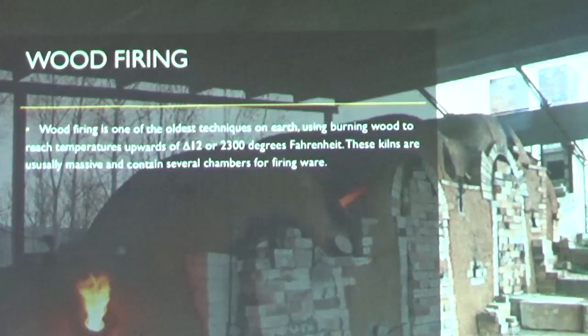This is one, as I said on here, it can reach upwards of cone 12, roughly 2300 degrees Fahrenheit. Now it can actually go higher, but then you start damaging the inside of the kiln. And it's amazing that you can do this through natural aspiration. There's no fans, there's no electricity powering this thing. It's simply designed and built so the airflow just keeps cranking the heat up, and up and up and up with wood. You wouldn't think it could do that, but it's pretty amazing.